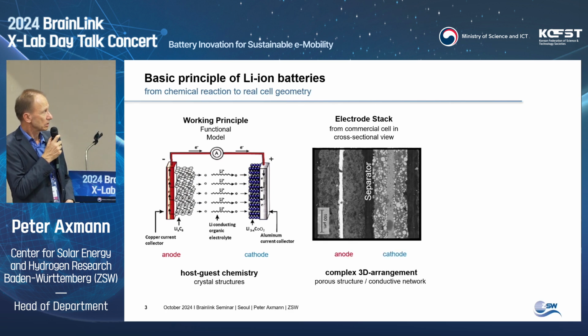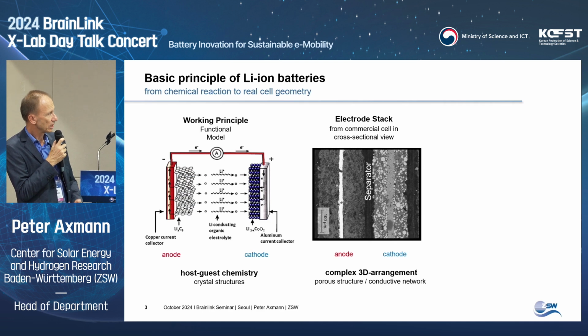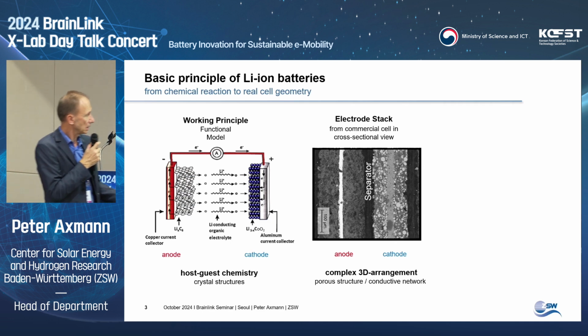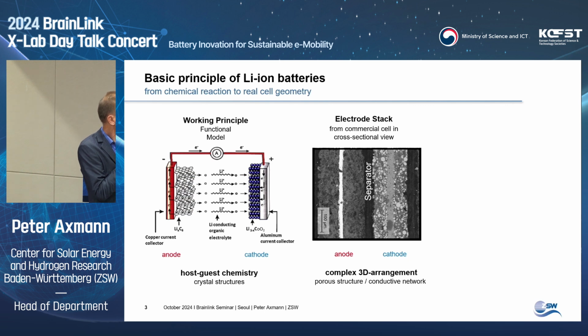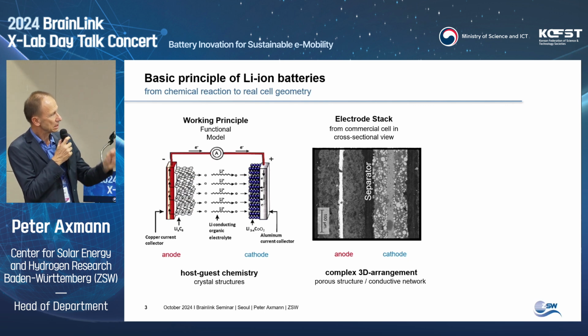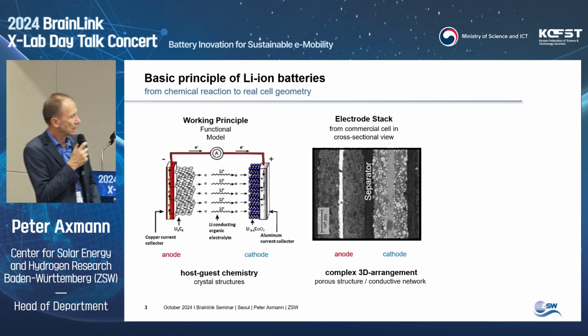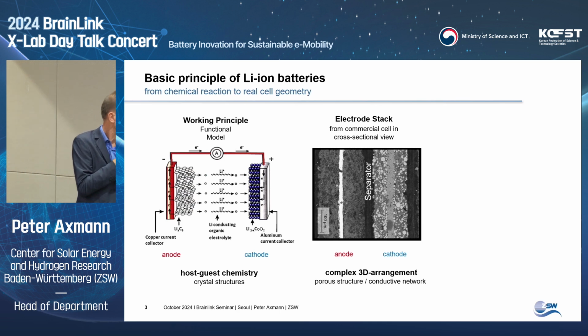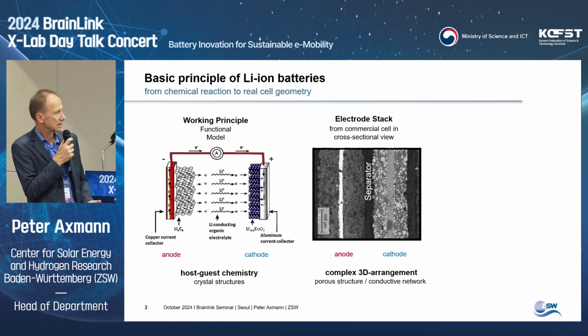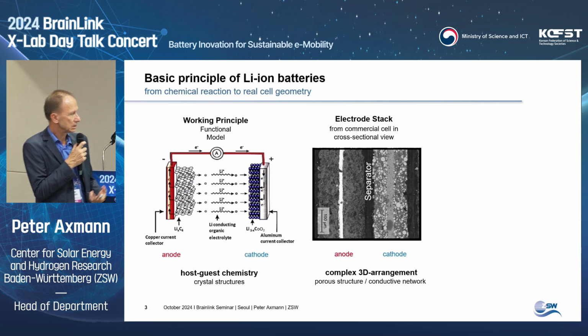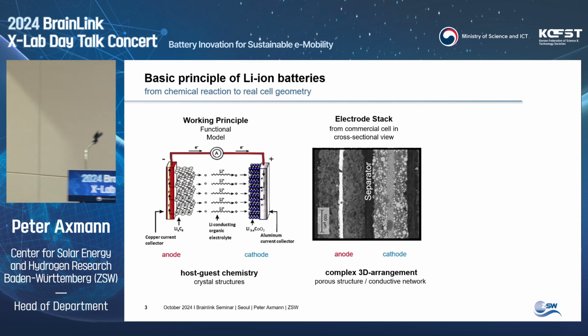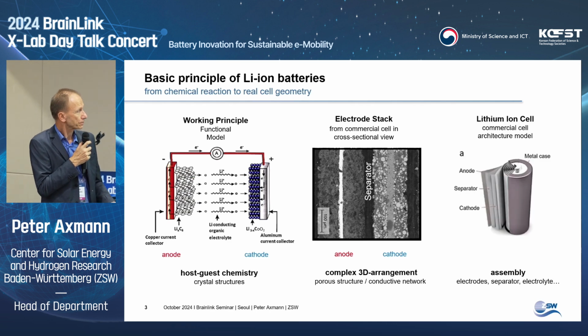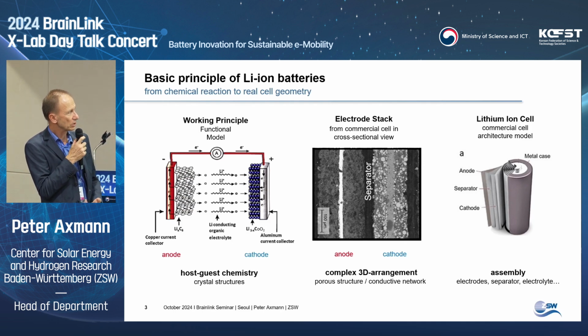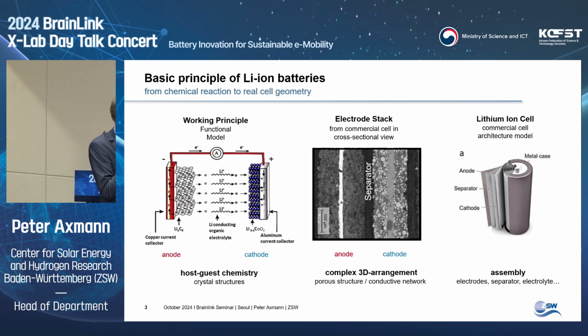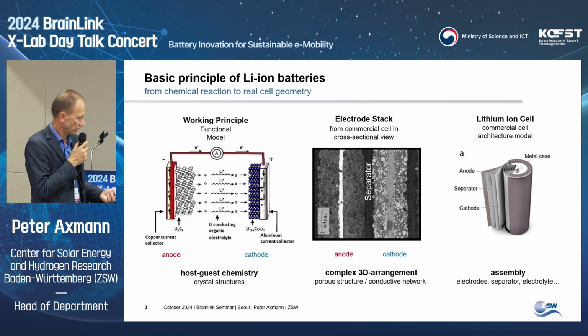And a real electrode stack, if we cut it and look with a cross-sectional view with SEM on this material, we see here on the left-hand side the anode, on the right-hand side the cathode, separated electronically by the separator. And these electrodes are a complex 3D arrangement with a porous structure to allow electrolyte access for the lithium transport, and a percolating conductive network for the electron transport to the current collector. So these electrodes are long tapes, and they are coiled up to form cylindrical cells, or they are stacked as prismatic cells or pouch cells.